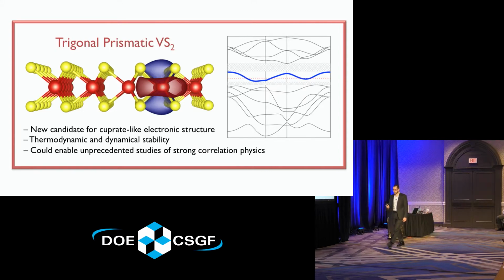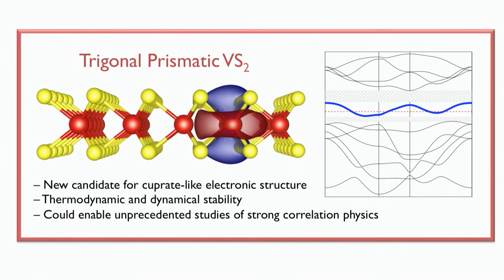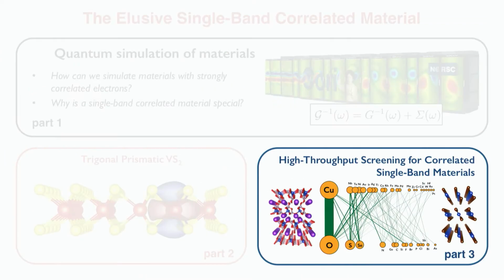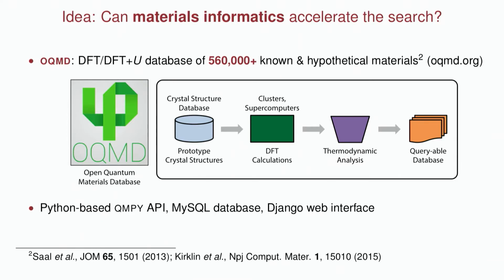Another thing we wanted to do is to see if we could more systematically look for additional compounds. In particular, we wanted to see, can this emerging area of materials informatics accelerate this search? Can we find more things that, like trigonal prismatic VS2, seem to have this kind of desired electronic structure? So what I've done is I've used what's called the Open Quantum Materials Database, or OQMD. This is developed at my institution at Northwestern University, and it is a database using density functional theory as well as DFT plus U, so the same level of theory, of over 500,000 known and hypothetical materials.